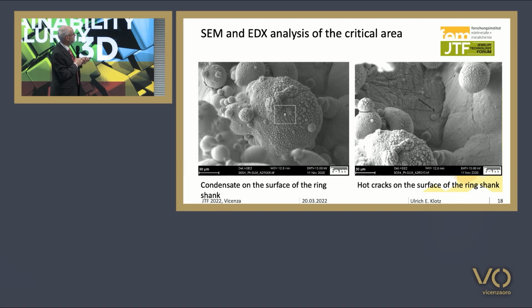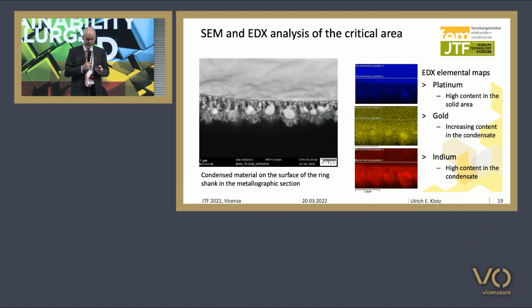So if you look here at the surface, we see a very porous, spongy surface. It looks like some material was there as a vapor and condensated on the surface. And we also see some hot cracks, which can occur as an effect of overheating.